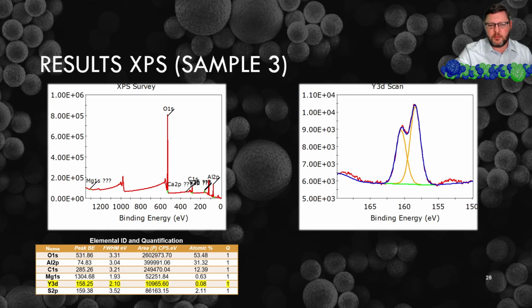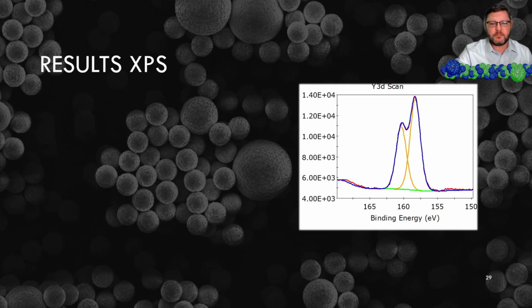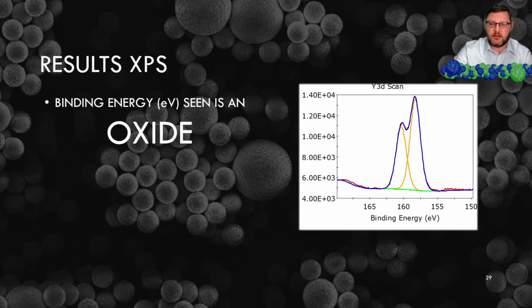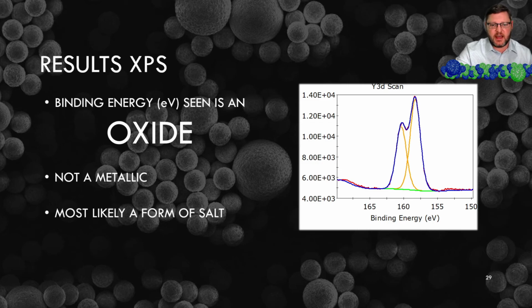Now our next sample showed pretty much the same thing, but it looks like there's a lot less yttrium, so it may just be the sample had less spheres in it. Only about 0.1% yttrium in that, and then the majority of it was carbon. So the binding energy seen with the XPS says that the yttrium is an oxide. It is non-metallic. Most likely it's a form of salt. And it is not a simple oxide. So we got a little bit of that surface composition there with the XPS, a little more characteristic there.